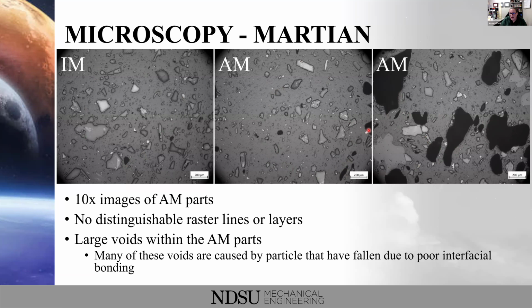And so where do they come from? Some of them we believe are particles that have fallen out in the polishing process or the cutting process. So we take broken specimens from impact testing, flexural testing, and so on. We cast them in a thermoset and then we polish them before we look at them under a microscope. And so some of them have fallen out, which indicates to us that there is a lack of adhesion between the particle and the polymer. That one is due to uneven wetting, but there should be a good bond between the mineral and the polymer, because we see in injection molding that there is a good bond between those materials.